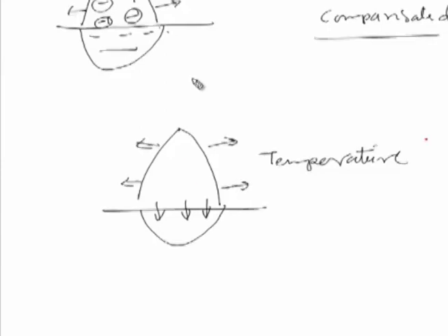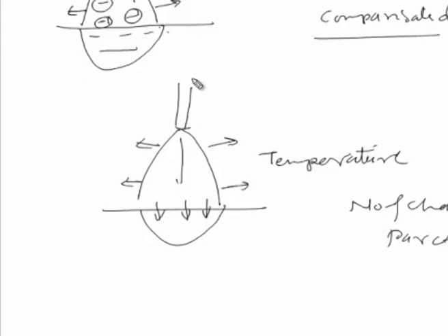the charged particles in the arc gap. So, the loss of heat to the surroundings and to the base material also should be compensated in order to have a sufficient number of charged particles in the arc gap, so that sufficient electrical conductivity across the gap can be maintained and the flow of current can continue to maintain the arc.